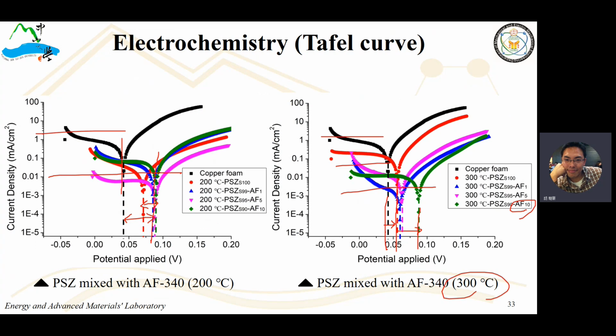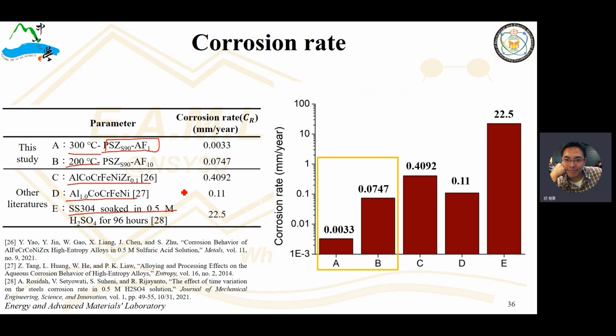So what is the result? It shows that the coating that we made has the lowest corrosion rate, even compared with the high entropy alloy. Even though the high entropy alloy has stronger mechanical properties, it's very hard, very strong, from the corrosion point of view it's really nothing. This high entropy alloy is nothing for anti-corrosion.